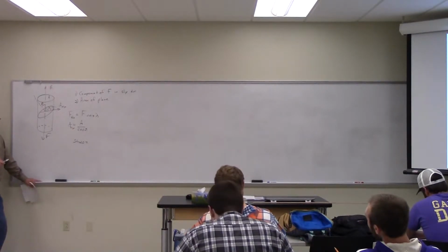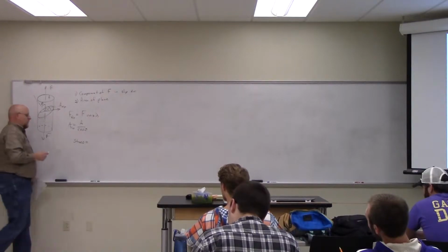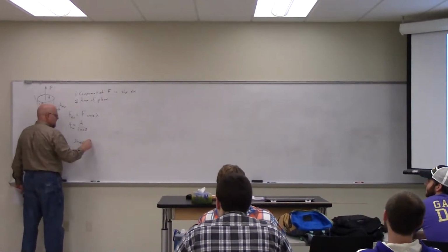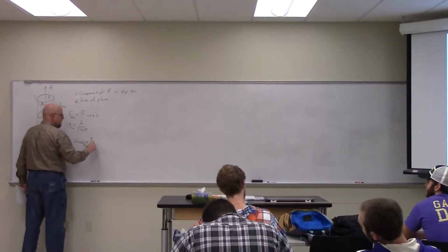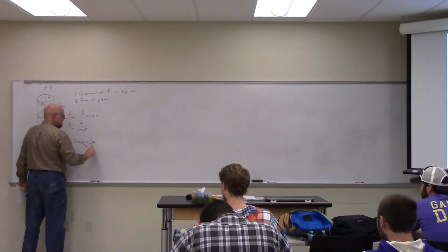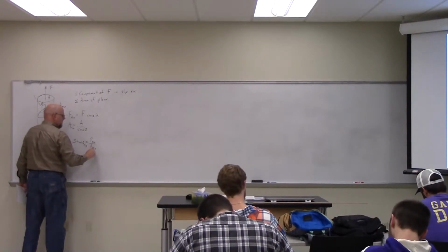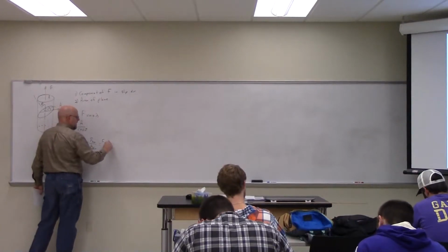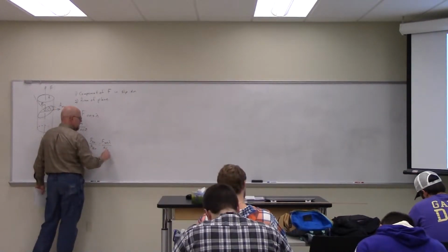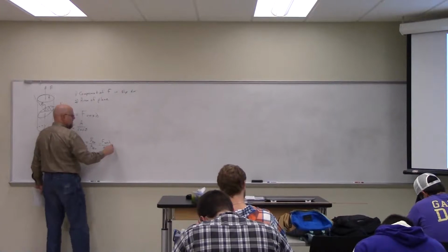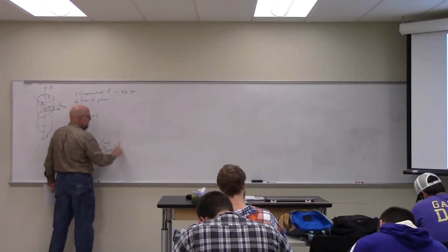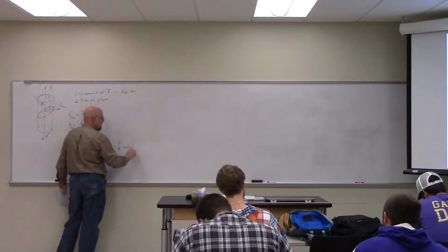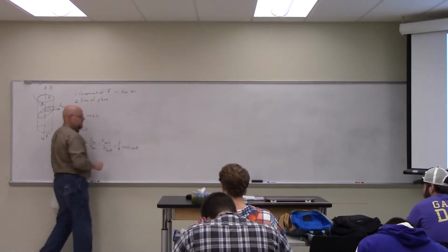How do I calculate stress? What's that? Force times area. Nope. Force divided over area. So the slip force divided by the slip area is going to give me the stress. So that's going to be F cosine lambda divided by A over cosine phi, equals F over A times the cosine of lambda times the cosine of phi.